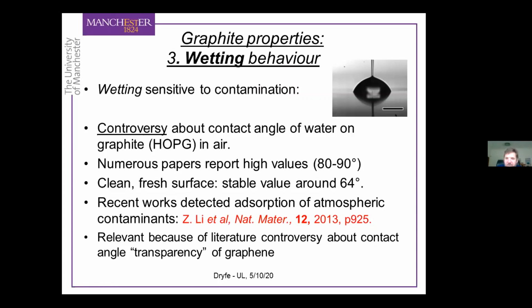So the image you have here, if you can see it, is a droplet of electrolyte solution on graphite, again on basal plane graphite, and this is viewed through a microscope. The scale bar here, I think, is probably 10 microns, and what you're seeing is the pipette at the top here, which is used to inject the electrolyte onto the graphite surface. And the reason you see a reflection is because the way we're illuminating it, the graphite acts as a mirror. So this is the mirror image of the droplet you see here, and the mirror image of the pipette.